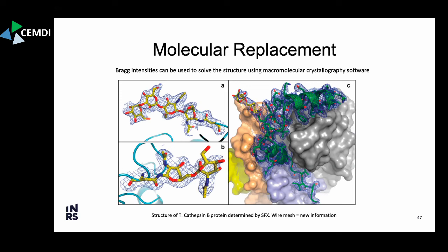And the idea of molecular replacement is that you use a structure which is similar, which is already solved, and you use the phases from that structure as a starting point, and then refine the electron density that you recover based on this initial model for the phases. And this works when you don't have a lot of extra information that you have to obtain.